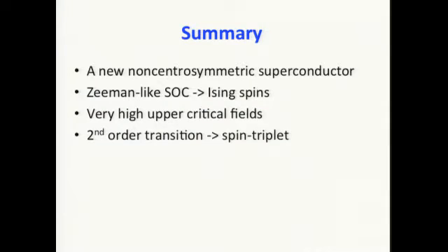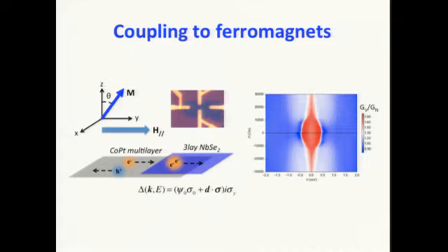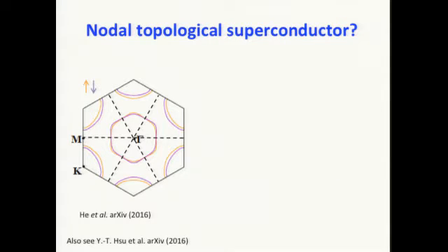Okay, so I just quickly put up the summary. We basically have observed this enhanced upper critical field, which is consistent with this picture of a Zeeman-like spin-orbit interaction, and it's supported also by measurement of the superconducting order parameter by tunneling measurements. And I will basically skip through. Well, maybe let me just mention this interesting thing to you, the possible existence of topological superconductivity